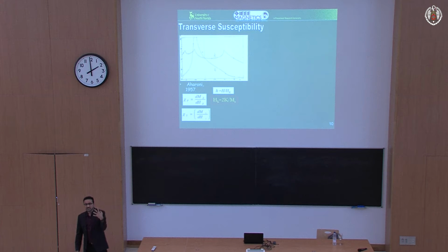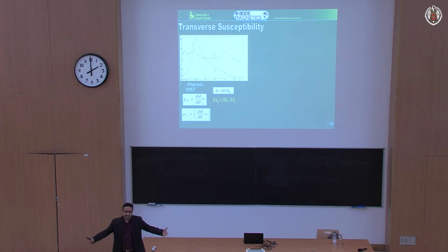In other words, you're measuring some kind of a stiffness of the magnetization. Okay? So this is reduced field, and you go from positive to negative polarity, and you can see that the conventional parallel susceptibility, as you would expect, has a singularity when you have the switching. Think of it as taking the first derivative of your hysteresis loop. So wherever the largest slope changes, you see a peak. And he pointed out that if you look at the transverse susceptibility, in addition to the switching peak, you also have two peaks that are symmetric, and they happen to be at the anisotropy field for this system. And the physics of this is reasonably clear, because, as I mentioned in the equation, it's a competition between the Zeeman energy at high fields and the internal magnetic anisotropy. So you have a crossover, and that's what gives rise to these peaks.